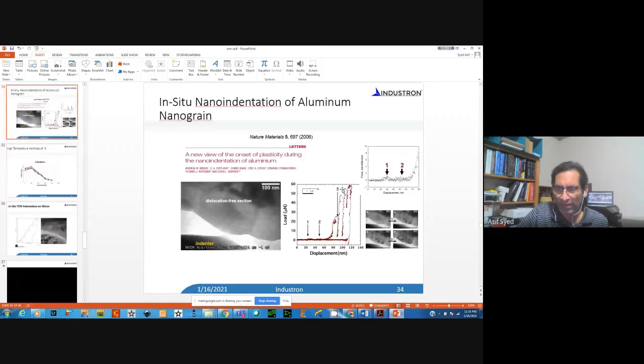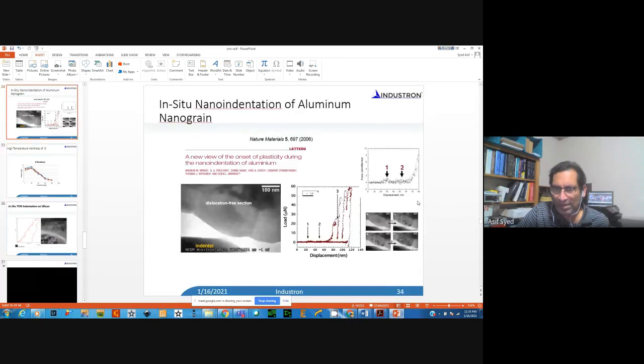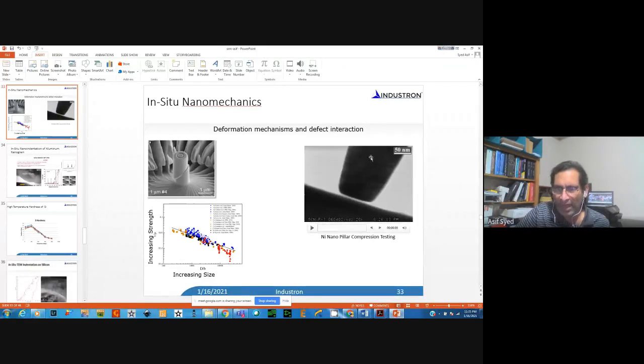So this is basically the material on a wedge, and the electron beam is passing through the wedge, and then you're indenting perpendicular to the wedge. And here with the nickel, this is a cylindrical sample, and this is electron transparent. Again, it is only 50 nanometers, maybe about 100 nanometers, still electron transparent. So we can apply the flat tip, compress it perpendicular to this cylinder, and the electron beam is passing through the thickness of the material.